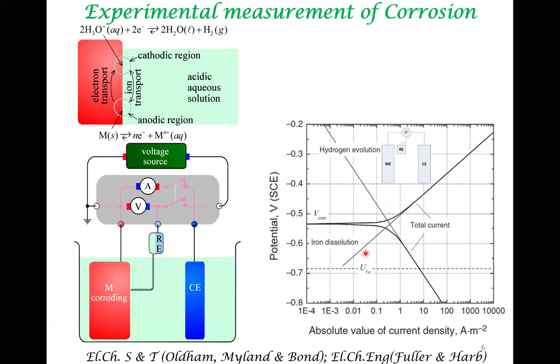we obtain these plots. What is being presented here is that the y-axis has information on potential, and here we are indicating corrosion potential. At corrosion potential, the net rate of generation of electrons from the anodic reaction matches with the rate of consumption of electrons in the cathodic reaction. That's the way we define corrosion potential.